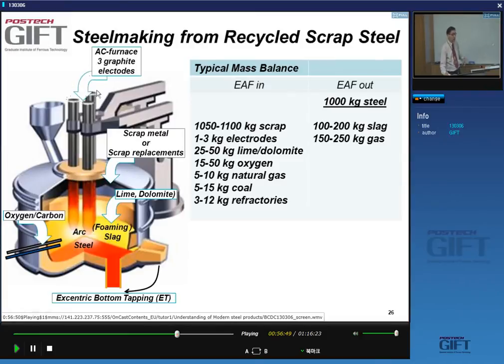The carbon in this steel comes from the fact that you use graphite electrodes, and they get used up as you work, so that is one of the reasons why you do increase the carbon content in the steel. So what are typical things you get in? Well, you will melt about a ton of scrap. The next biggest thing is about 50 kilos of lime to make the slag. And what comes out is, for every ton of steel, about 100 to 200 kilos of slag and about 200 kilograms of gas.